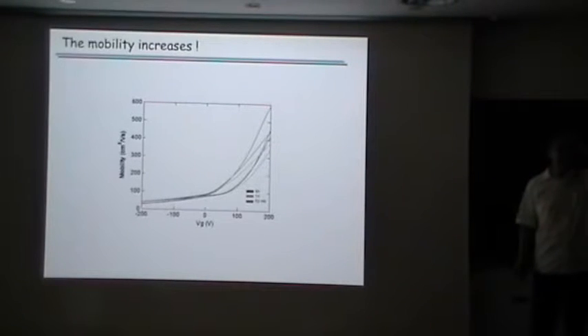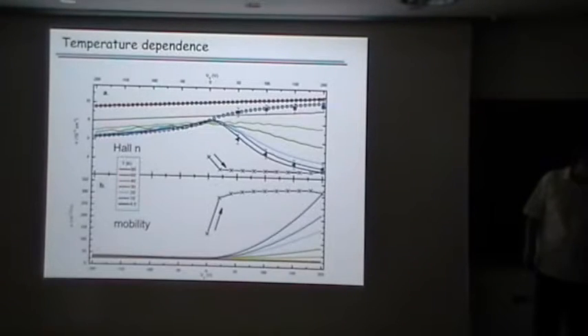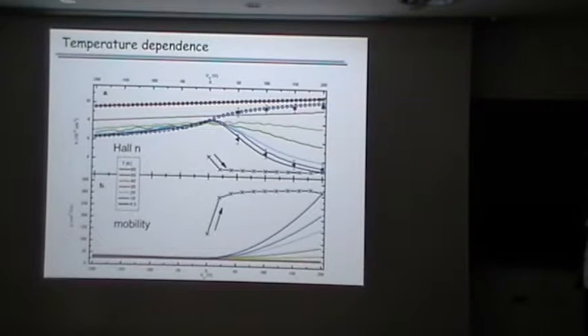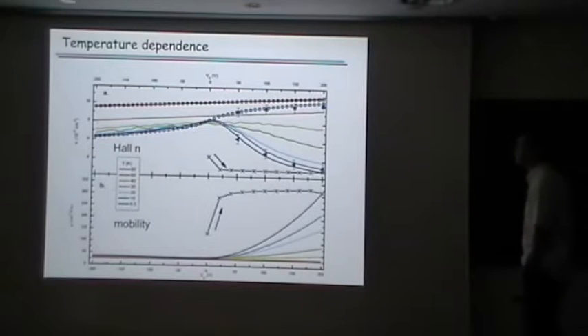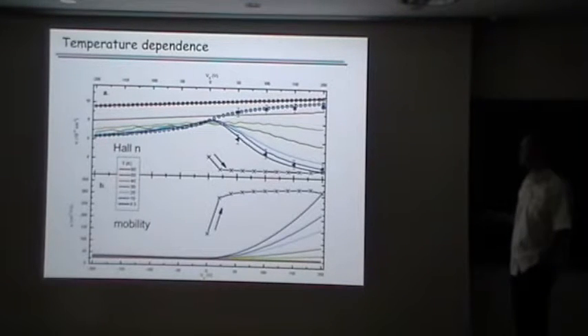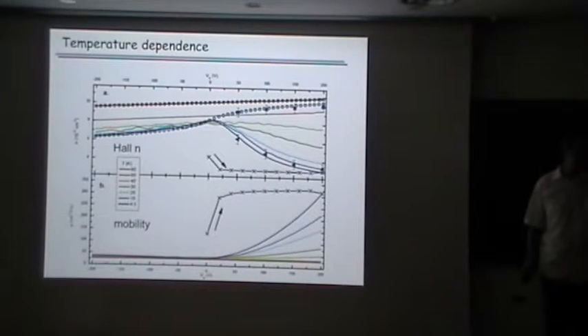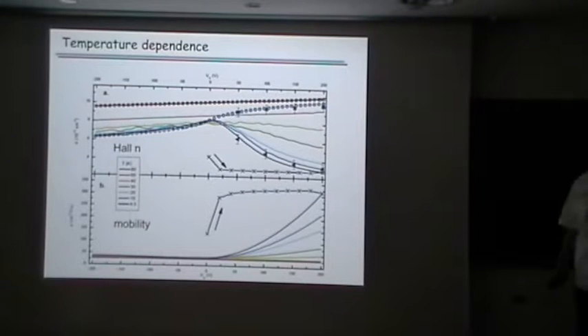We don't put 10 times more electrons in the system with the capacitor. So it's just not good. Now if we look at temperature, that's interesting, because again this is the Hall effect. This is the capacitance here at low temperature, and the Hall effect is going down. But when you increase the temperature, the Hall effect becomes completely linear, as you expect for a regular system, and this is the capacitance and the Hall effect. So it's matched exactly. So you know exactly the number of carriers you put in the system.